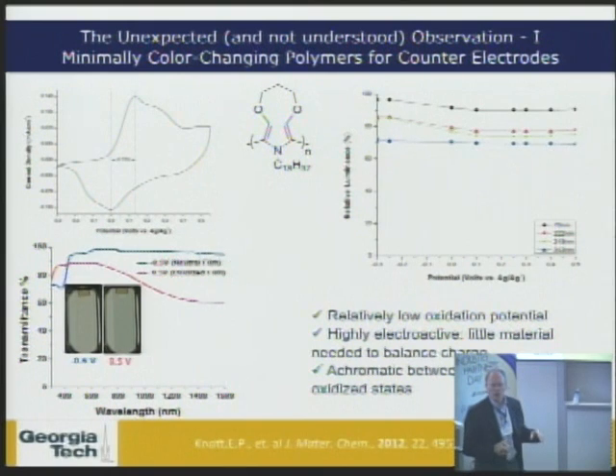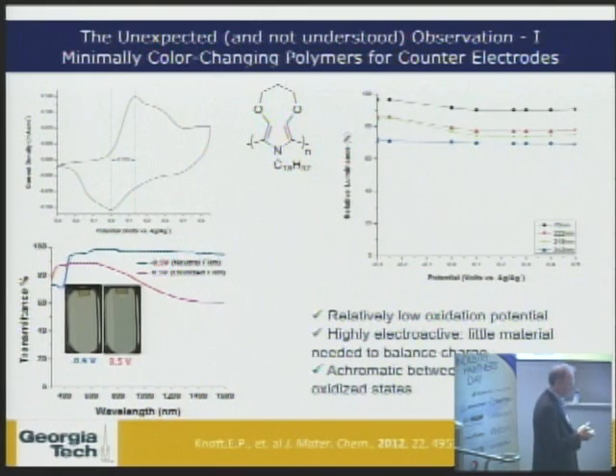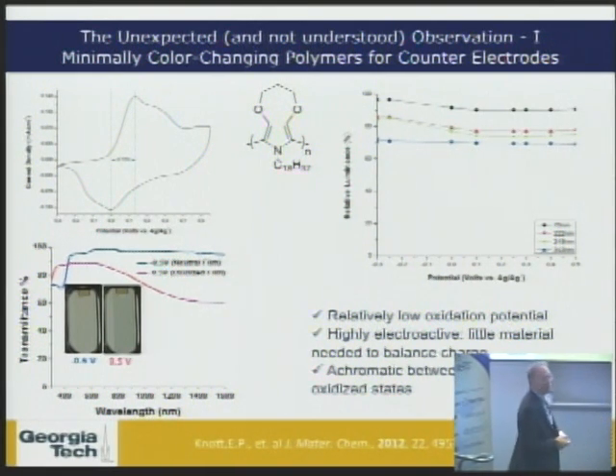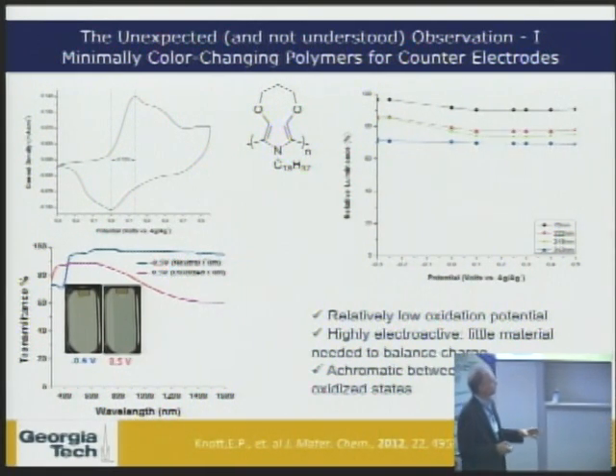Now, dioxypyrroles are the most electron-rich of all of the conducting polymers. They're the easiest to oxidize. But in essence, what we do is we break conjugation by putting a large group here, in essence, to force these pyrrole rings out of plane. Because it's so electron-rich, the electrochemistry of the polymer is still at a very low potential. It switches between its neutral form and its oxidized form very effectively.